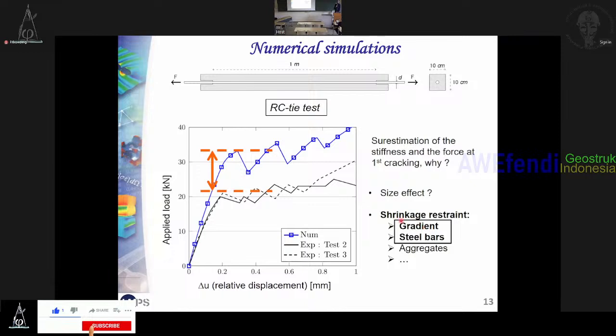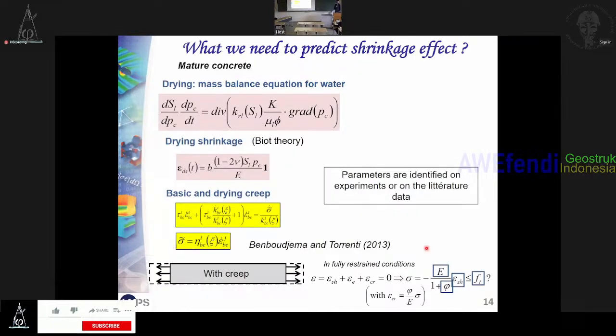We were looking at the effect of shrinkage. If you have shrinkage, you have an increase or decrease of mechanical properties, it depends. But you also have the effect that only the concrete is shrinking, and the rebar will prevent shrinkage of the concrete. I will not go into the detail of the model because it's quite classical. We have a partial differential equation to solve the drying problem. You can use the capillary pressure, the saturation degree, the relative humidity, whatever you want. We assume that drying is mostly related to the migration of water by permeation. We use Biot theory to retrieve drying shrinkage evolution.